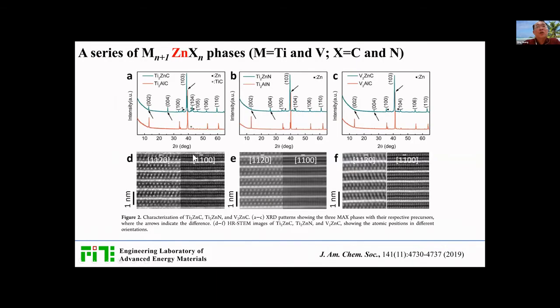So we can also use several other MAX phase precursors, and for example, we can use the 211 MAX phase, and we can use nitride MAX phase as a precursor. So there's no doubt that we got similar results, getting some new MAX phases.